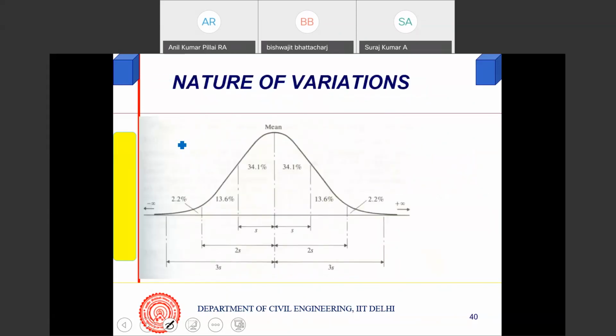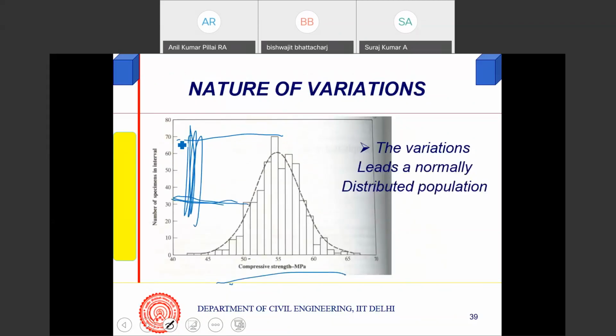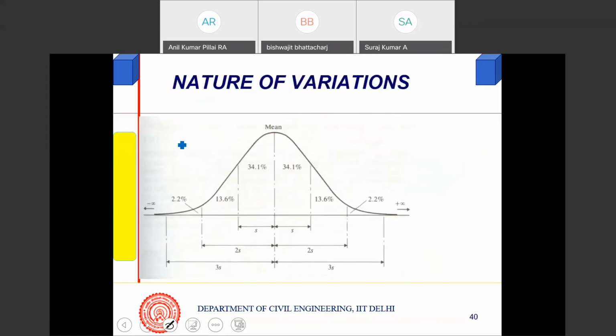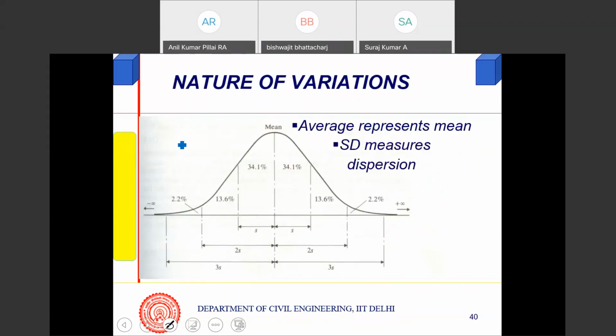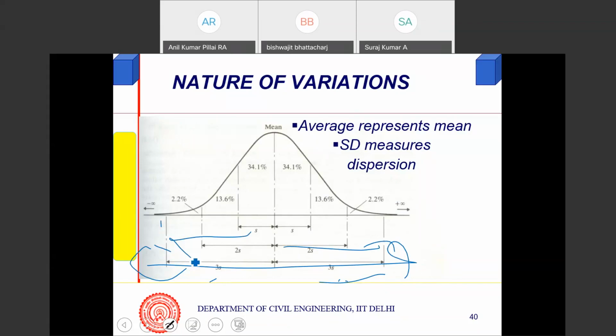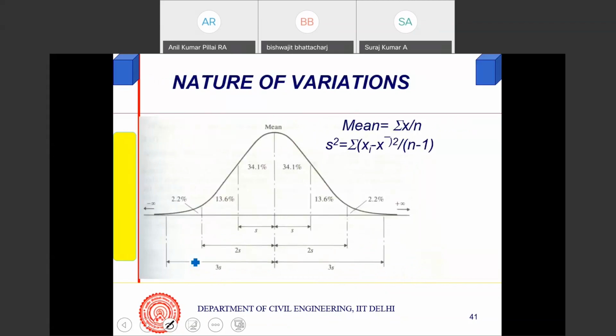And this can be normalized such that the area under the curve is 100%. If you divide by the total number of samples, each will be a fraction, and the sum of these fractions will be equal to 1. You can approximate this into a kind of curve, and the average represents the mean, and the standard deviation is the spread, right? And it has been seen as a rule, 6 standard deviation. This is 3 standard deviation, this is 6 standard deviation, because these are all relative measures. And for your characteristic strengths, this can be formed in this manner.